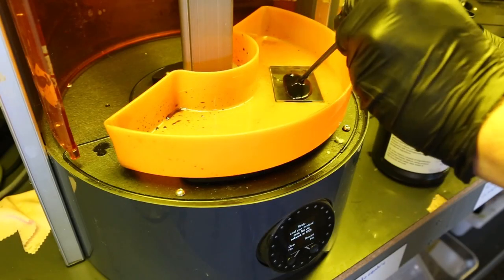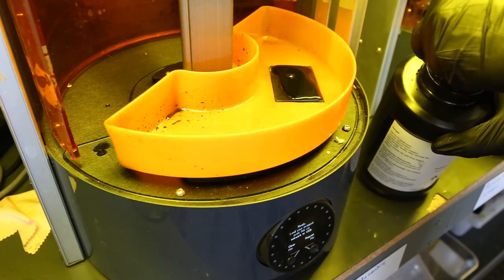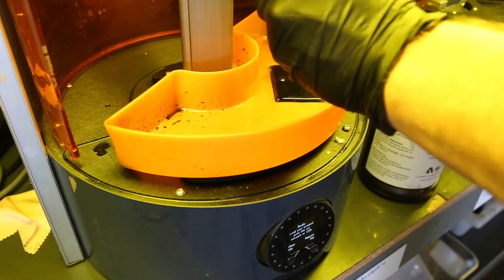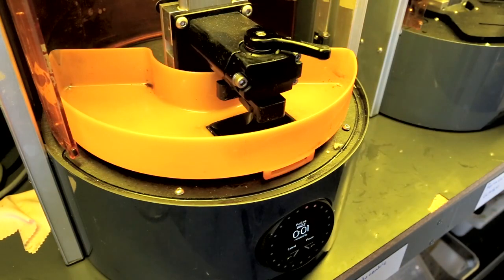Unlike a normal print, we don't fill up the tray with resin. Simply pipette a layer of resin directly onto the PDMS window. Also, the tray does not rotate between layers, and we do not use a build head. Then we run the print file, which only takes a little over a minute.